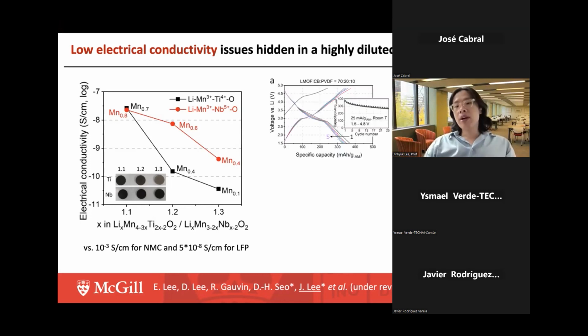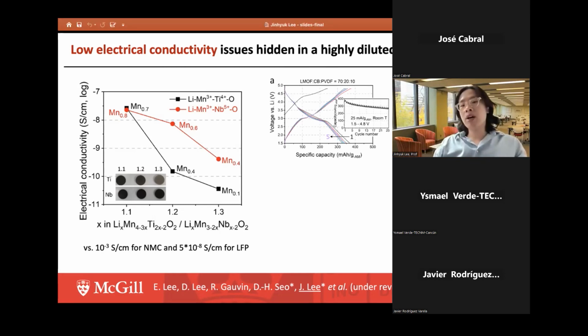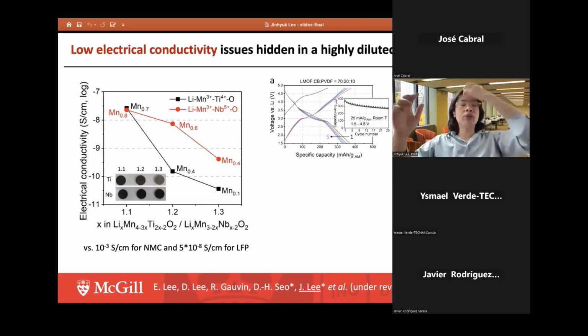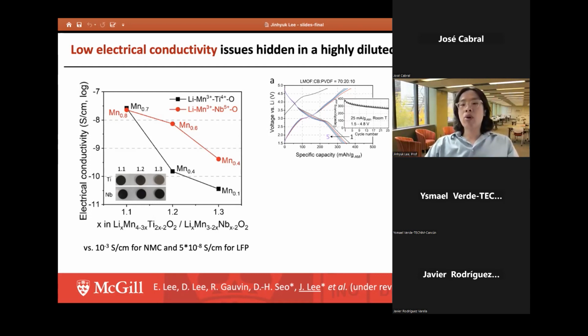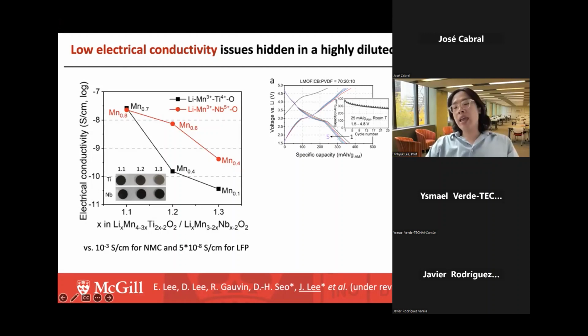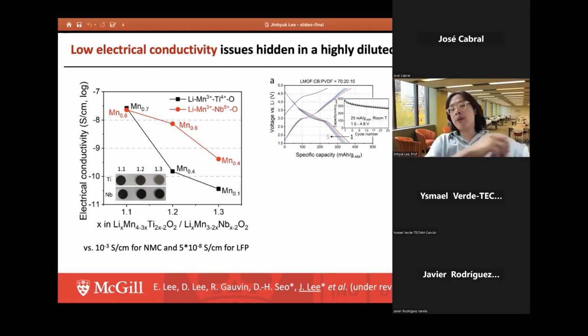For example, here I'm showing you the voltage profile of a so-called partially disordered DRX material. Now, if this active material is 70%, the carbon black is 20% and the binder is 10%, we see that the performance is quite impressive, delivering close to 360 milliampere-hours per gram with decent capacity retention. But now if you go to an 80-10-10 electrode composition, so now you have a lesser amount of conductive carbon, more active material.